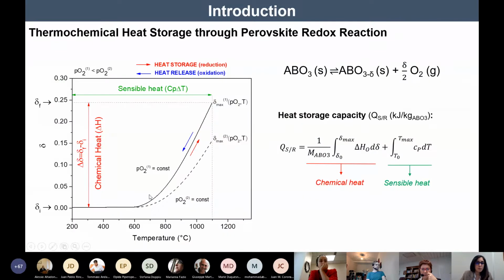The non-stoichiometric perovskite redox systems release oxygen in a broader temperature range with respect to stoichiometric reactions, like for example in the case of the binary oxides, in which the reaction occurs at a very specific temperature. The total heat storage capacity is given by two different contributions, the chemical heat and the sensible heat.